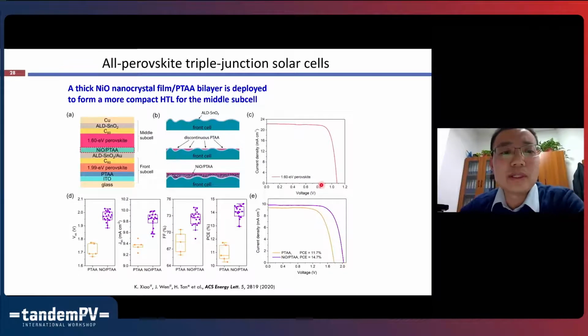But when we wanted to make the triple junction solar cell, one of the challenges is the front cell, because we have to use quite a high ratio of bromine in this composition. So the film surface is quite rough. And when we want to spin coat a PTAA hole transport layer for the middle subcell, it gives us a challenge because the VOC and also the fill factor are quite low.